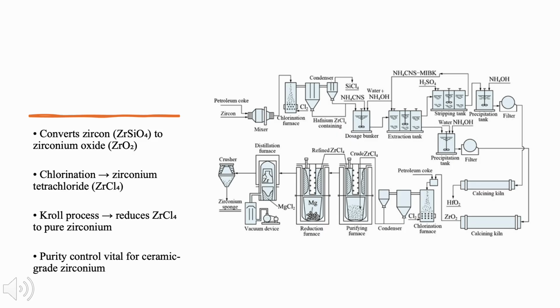The gaseous zirconium tetrachloride is then condensed into crystals and purified by fractional distillation. This is where the famous Kroll process comes in. Named after metallurgist William Kroll, it involves heating the purified zirconium tetrachloride with molten magnesium in a sealed vessel. The magnesium removes the chlorine, leaving behind spongy metallic zirconium and magnesium chloride as a byproduct. That zirconium sponge is later melted under vacuum to form ingots for metal applications, or oxidized back into ultra-pure zirconia